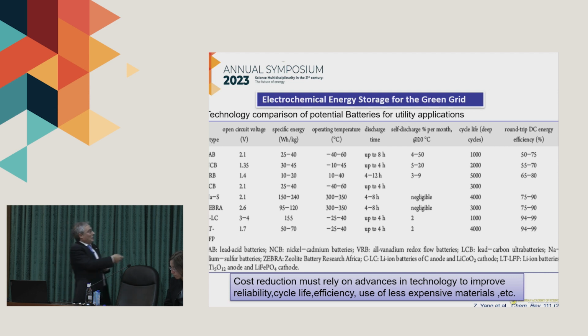Another one is graphite and lithium cobalt oxide. These have good energy density, but poor cycle life and good efficiency. And the last one is lithium titanate and lithium iron phosphate. We are using lithium in the anode, we are using lithium in the cathode, and the energy density that we have here is 50 or 70 watt-hour per kilogram. The question is, is it necessary for a stationary energy application to use lithium-ion batteries?